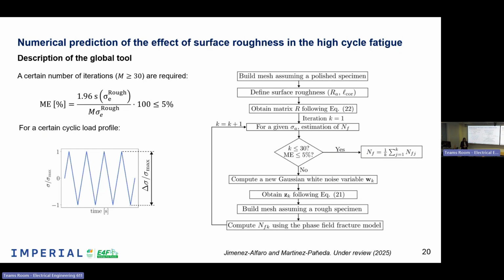For example, the average surface roughness, just typical measurements in a surface profile, or the correlation length, again the same, typical measurements that can be obtained in an easy way. Then after that, we obtain the matrix R, that was this original matrix that depends only on the correlation length and the initial position of the nodes.